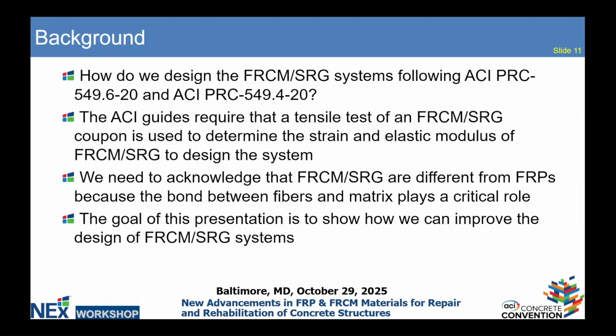So we need to acknowledge that these composites are a little bit different from FRP, because in FRP, we never typically see any issue between fibers and matrix. So the bond between the fibers and the epoxy resin is usually good enough that usually it's the bond with the substrate that is the problem. But in the case of FRCM and SRG, the bond between fibers and matrix can play a critical role. So the goal here is to understand how we can really improve the design, but really considering whether or not the tensile test that is currently used makes sense for determining the properties that then we're going to use in design.